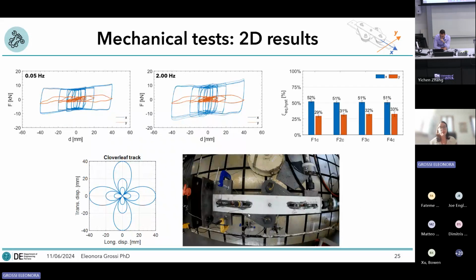And this is what happened when I applied the bidirectional waveform, which in this case is a cloverleaf. You can see that the hysteresis cycles are still rectangular, which is good, and they are also unaffected by the frequency increment. Only this time the transversal direction is slightly less rectangular, so the equivalent damping is slightly smaller than the monodirectional test. However, you can see that the damping coefficients are still high, and also there is not such a high variation during the test.